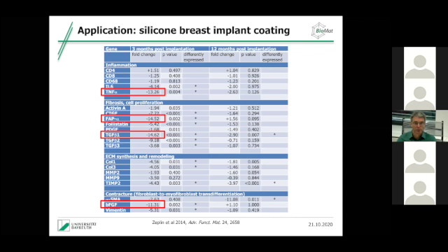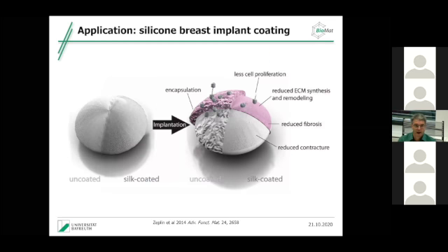But if you look at the factors, all the others are negative, which means they're all much lower than in the uncoated control. Inflammation factors, fibrosis factors, TGF-beta1, which is a very important marker for capsular fibrosis, severely reduced. Contracture markers, fibroblast to myofibroblast transdifferentiation. This is an indication of wound healing, pretty much reduced.